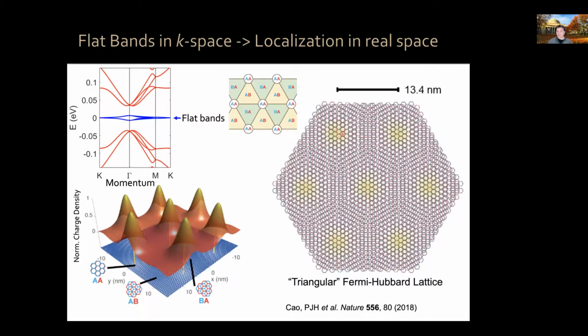In a slightly more realistic schematic, these AA regions, which are denoted here in yellow, are separated by about 13 nanometers. And electrons like to sit here, so this is going to form the equivalent of a triangular Fermi-Hubbard lattice in cold atoms, except that it's not really triangular, it's a honeycomb lattice because these AB and BA regions are not identical. And it also has a special topological structure that does not make it really analogous to a Fermi-Hubbard lattice, but you can think of it a little bit like that.